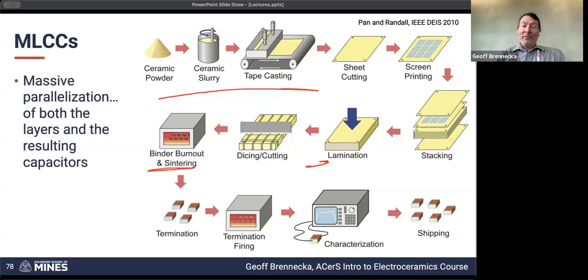Then we have to sinter. So in this diagram, the binder burnout and sintering is just one simple step. You throw it in an oven and you're done. But as Shannon alluded to, think about what's actually happening in this case. We have an electrode layer of some sort. Let's say it's platinum, or it's silver, or it's nickel. It's a metallic layer of some sort. And then we've got our dielectric layers on top of it.